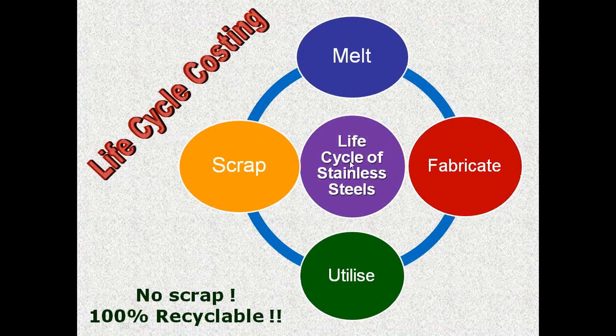The most important point I feel is that this is one material where life cycle costing is very important. If you look at the life cycle of stainless steels, from the melt, you can fabricate various components and use them in the industry for various applications. Ultimately, it doesn't become rust that you throw away. It becomes scrap. The scrap can be remelted. So by secondary melting and improving the quality, you can again go back to use these stainless steels for further application. It's as good as I can say no waste, 100% recyclable. That's the most important economical point.